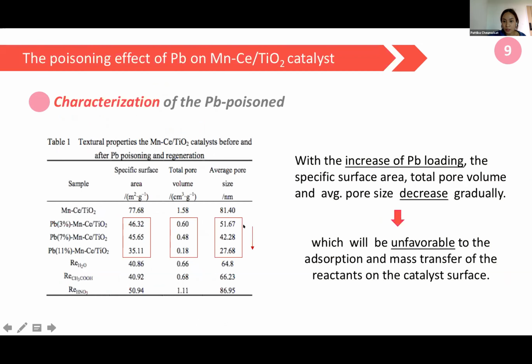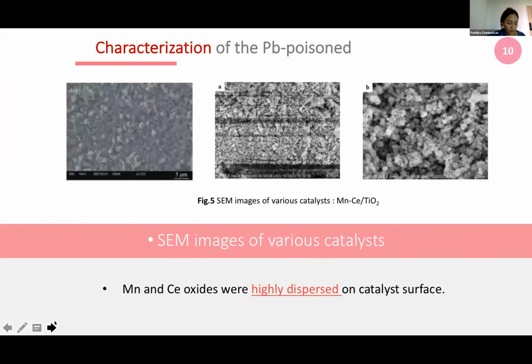With the increase of Pb loading, the specific surface area, total pore volume, and average pore size decrease, which will be unfavorable to the adsorption and mass transfer of the reactants on the catalyst surface. The figure shows the SEM image of various catalysts. Manganese and cerium oxide were highly dispersed on the catalyst surface.